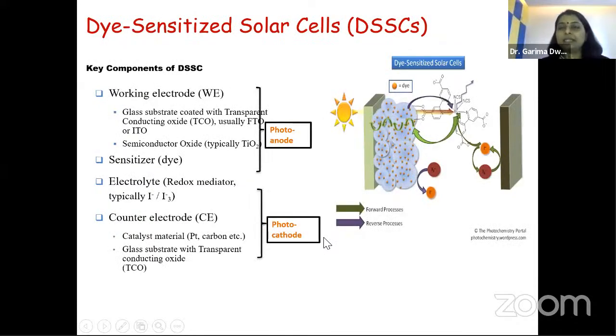If you see the DSSC, it is a sandwich type assembly. There is one working electrode, one counter electrode, and between those electrodes, the electrolyte is there. On the working electrode part, this is the photoanode. In the photoanode, we need high surface area. So why do we use nanoparticles? Nanoparticles are very small in size, so the surface area will be high, and more dye can be absorbed on the larger surface area.